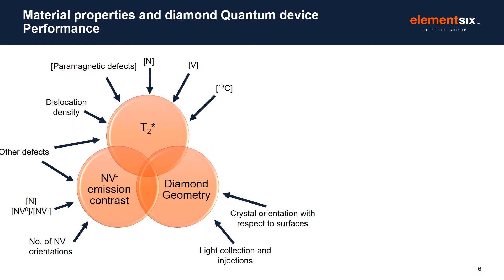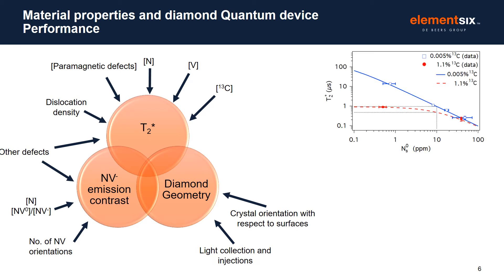So we need to consider all these factors for diamond in quantum technologies. There are three main things to consider when optimising material for a quantum device: there is T2 star — that's the spin lifetime with the NV defect; there's the geometry of the diamond, so how are we going to get the green light in or the red light out of the diamond in an optimised way; as well as the NV contrast emission, that is the amount of light you're getting from your NV of interest versus any other background light. As a material grower, we need to think about the various different things that can influence these key factors. For example, dislocations impart strain which can affect T2 star, or the amount of nitrogen can also limit T2 star. This is what we see in this plot where T2 star is plotted for different nitrogen concentrations.